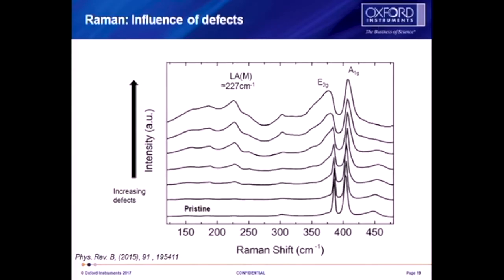that is left behind. And Mike, when he was talking about his ALE etching, was saying that the 227 peak, which is the longitudinal acoustic mode peak, wasn't actually present. But this seems to be present when, in this experiment, they put a pristine piece of molybdenum disulfide in and then fired ions at it and deliberately damaged it to see what came out of it. And you can see multiple peaks, but this one was the biggest and most characteristic. What we have evolved is the fact that the ratio between the LAM peak and this characteristic peak gives you a good sign of the quality of the material that you're depositing in the system.